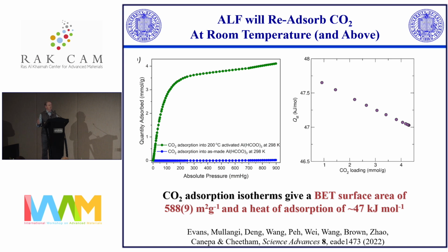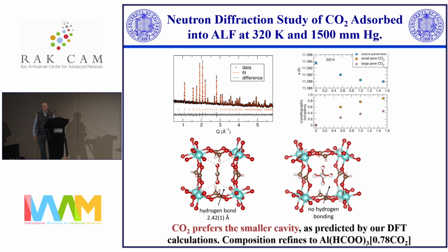So this is a high surface area MOF material that will absorb CO2. The green line is the CO2 isotherm at room temperature. The blue line on the bottom is what happens if you don't activate the material. If you take the material that's been described before that has stuff in the channels, of course it doesn't absorb anything. So it will reabsorb it, and so this looks quite exciting for various applications.